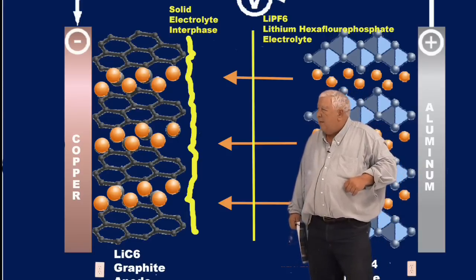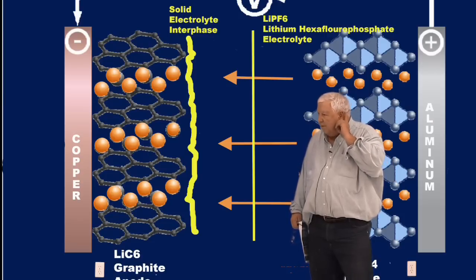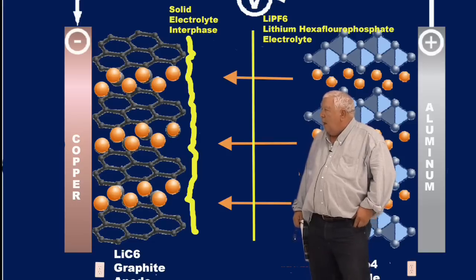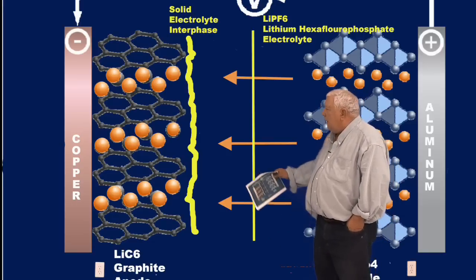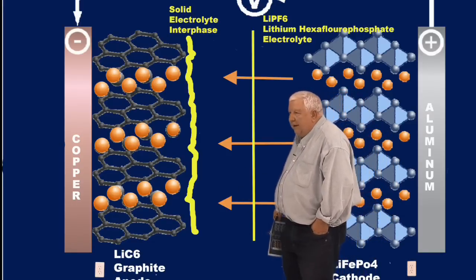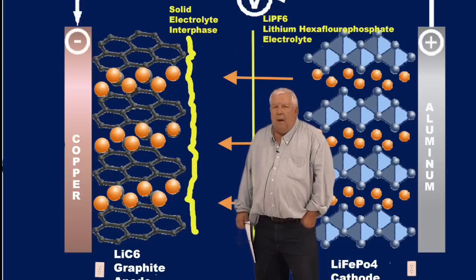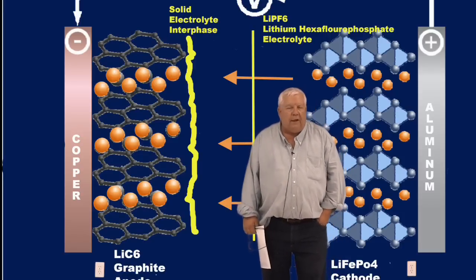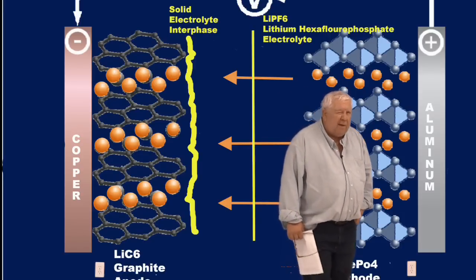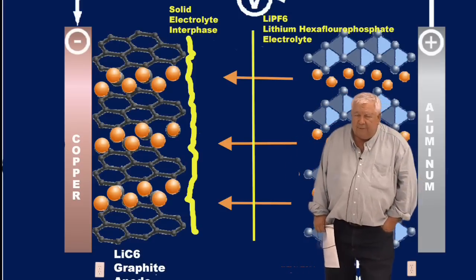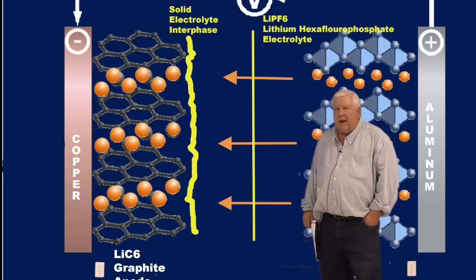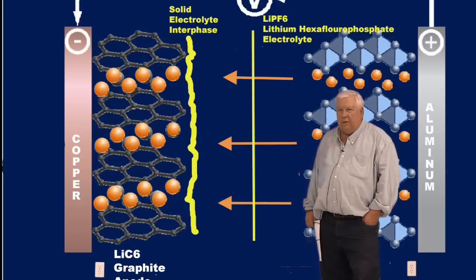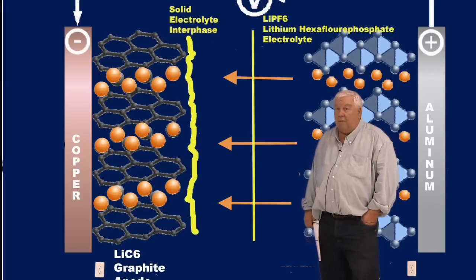The effects of temperature. Increased temperatures cause a lot of these things to happen more quickly. But the biggest problem is that our electrolytes, again, begin to gas, and most especially the ethylene carbonate at about 90 degrees centigrade. There's some other things that happen before that, and so we say the band of 70 to 90 degrees centigrade is a bad place to be with these batteries internally, certainly externally.